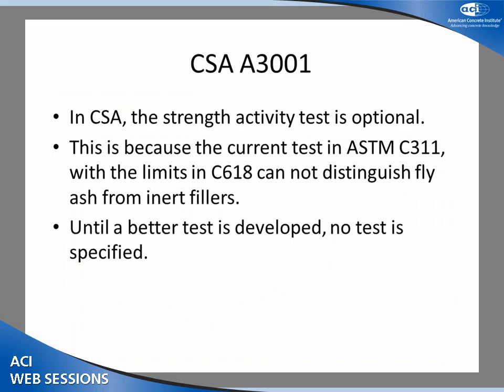The other thing, since I'm talking about random elements related to fly ash: we use the same strength activity test in the CSA as the ASTM C311 test, and we had the same test limits as in C618. But then we made them optional because the current test method in C311 and the current limit in C618 mean you can take inert fillers and pass the test. So why bother doing the test? And so we just said, look, it's optional. We're not going to mandate anybody doing that test because it doesn't tell us anything, until somebody comes up with a better pozzolanic test or a better test limit to evaluate it.